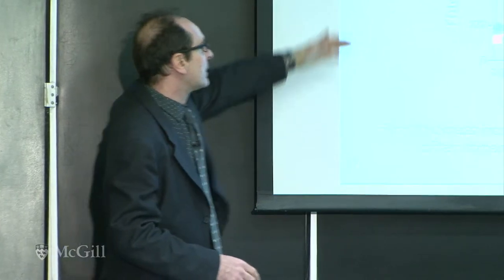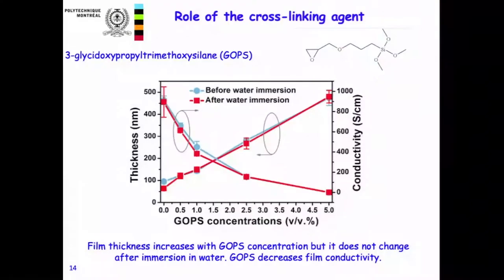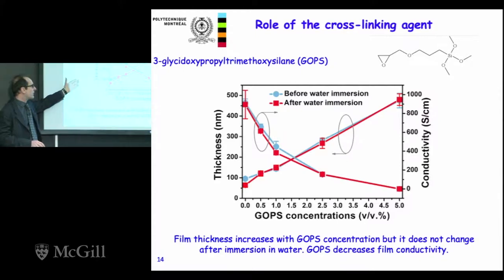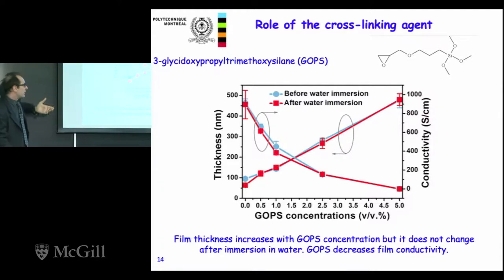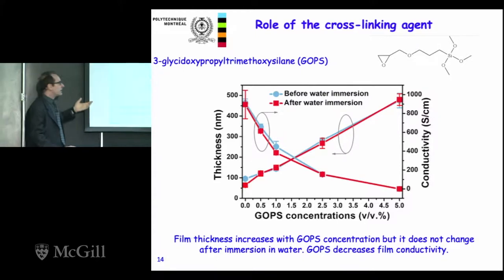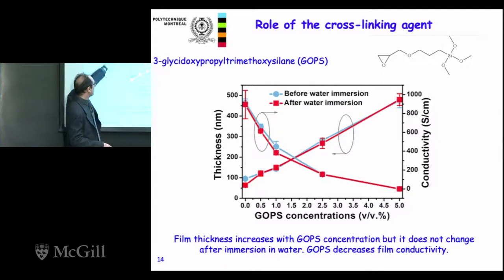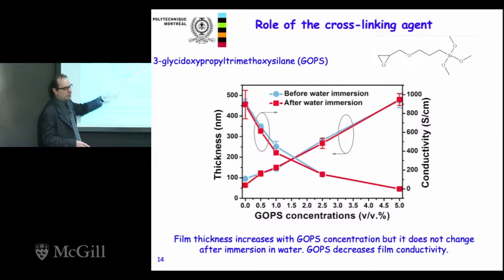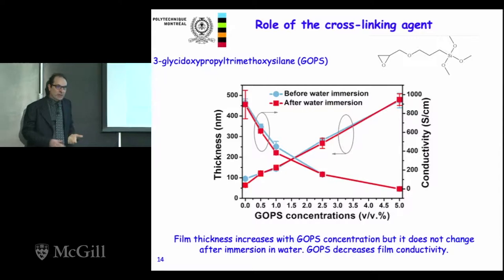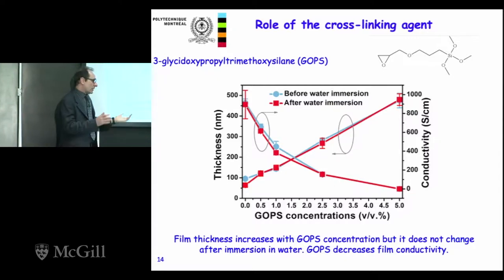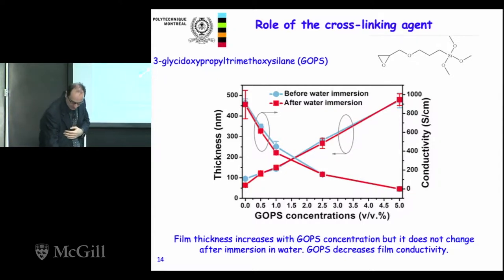So this is where the cross-linker comes to help. For instance, here, we see that if we add the cross-linker to the film, you see that here is the thickness. The two colors correspond to thickness before and after water immersion. You have no variation of the thickness in this case if you immerse the film in water. Of course, if you add a cross-linker, you decrease the film conductivity. So this is where you have to find the compromise between stability and high conductivity.